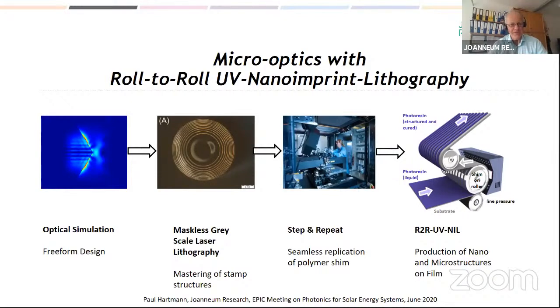Here you see, for example, a freeform Fresnel lens, which has freeform surfaces, but cut in a very thin shape into a Fresnel principle. So when we have the design, we go to a mastering process, which in our case is most of the time a maskless grayscale laser lithography. And we do this on 6-inch, more details a little bit later.